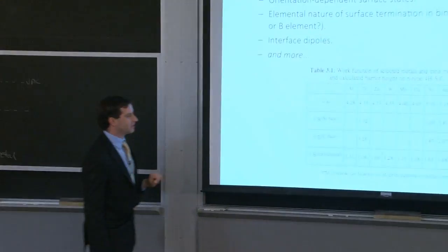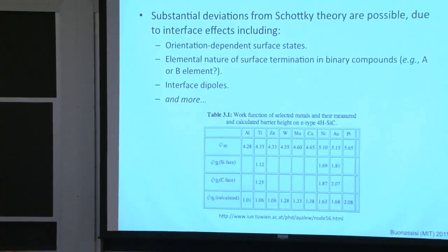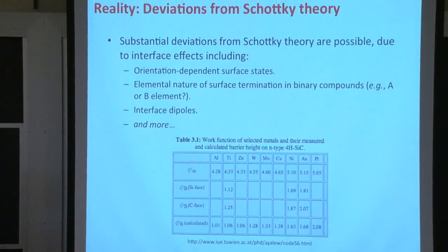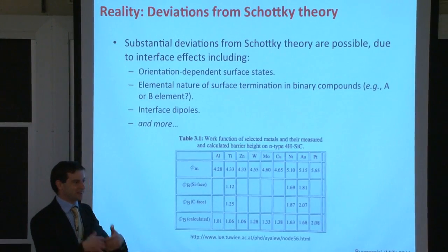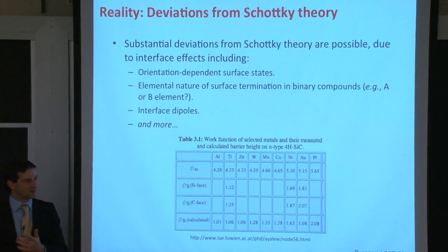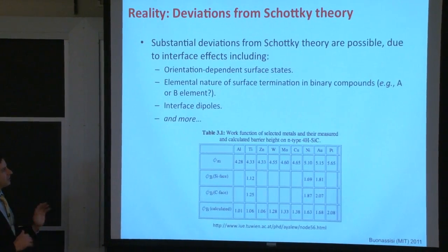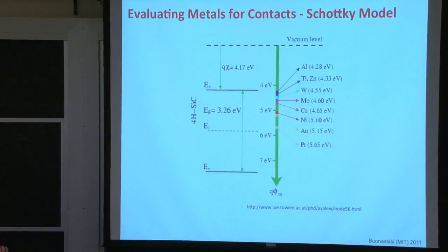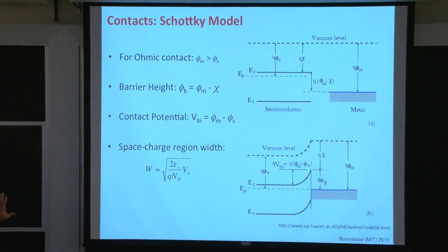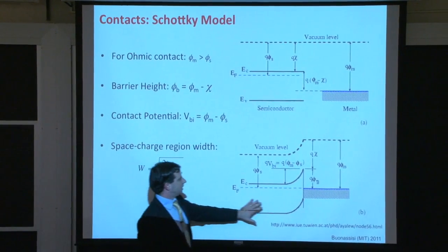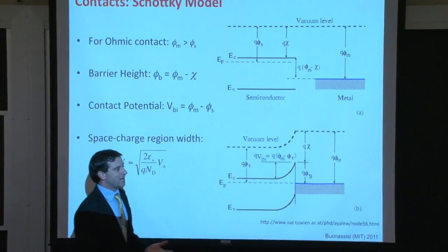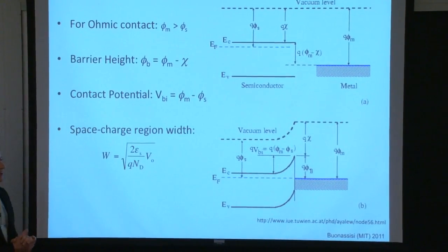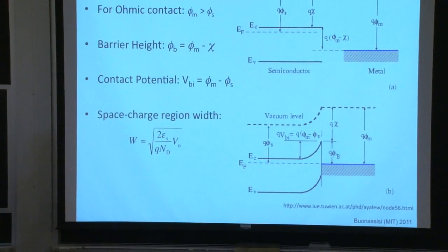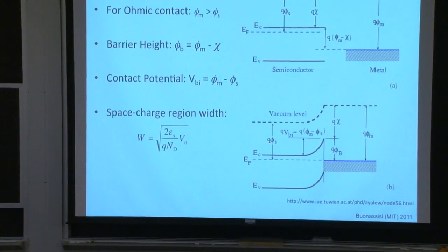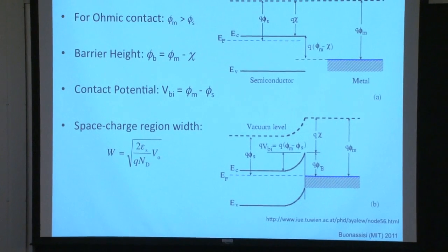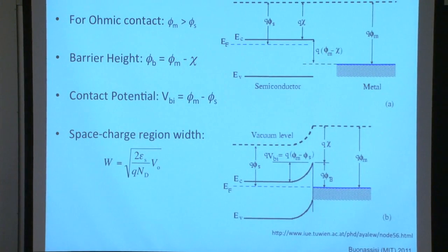So we can as well vary the density of defect states here at this interface that can trap charge. And again, with the accumulation of charge comes a field. With a field comes a deviation of the potential. So what we've done for ourselves is effectively we set up, using this Schottky model, the energy band diagram of a metal-semiconductor contact in its simplest case. And what we're going to do over the next few slides is explore some of the more complexity behind what goes into a semiconductor-metal contact.